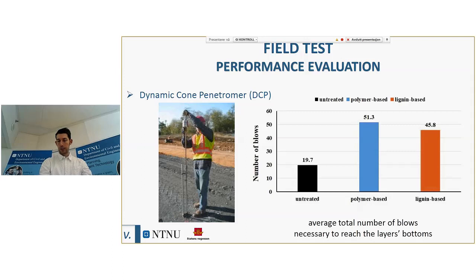And this similar graph portrays the number of blows which was necessary to reach the end of each one of the three areas. When it comes to the untreated area, almost 20 blows were sufficient. But then we needed almost 50 blows when it comes to the polymer-based layer to reach the bottom, and almost 46 when it comes to the lignin-based additive.